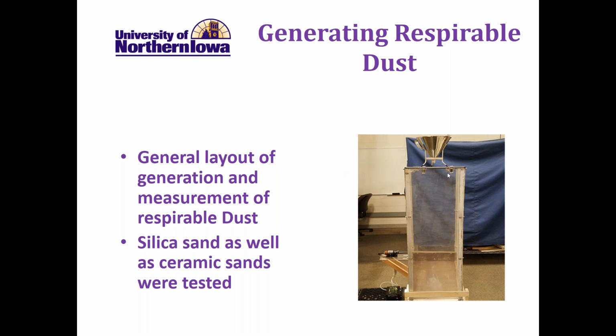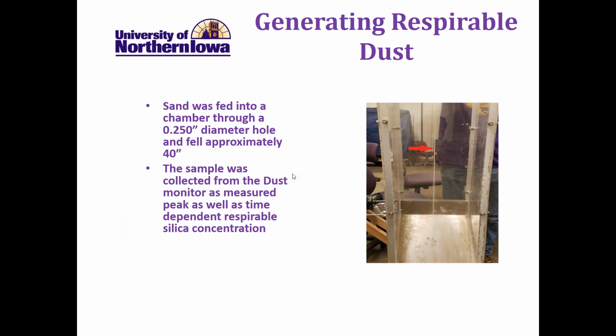The general layout: we have a funnel. We drop the sand through a 1/4-inch diameter hole, falling approximately 40 inches. Now this is done dry, unbonded. And then the sample of dust was collected from the dust monitor, measured as peak as well as time dependent. So we could measure both the amount of dust coming off and also the peak amount that would be measured in the device.